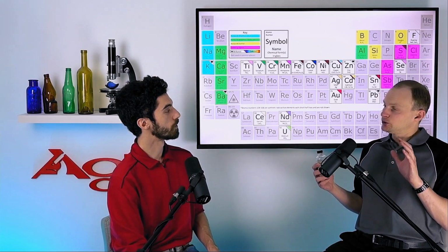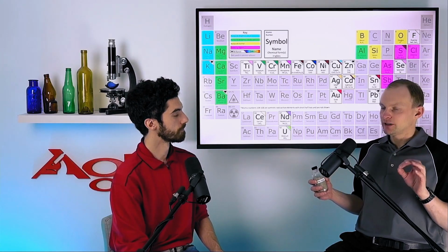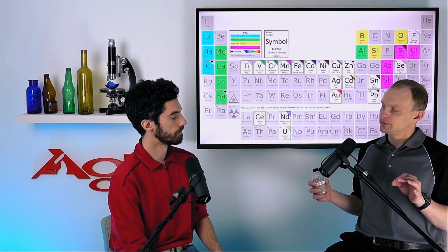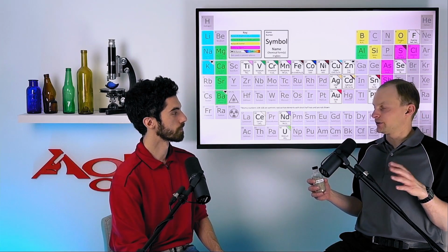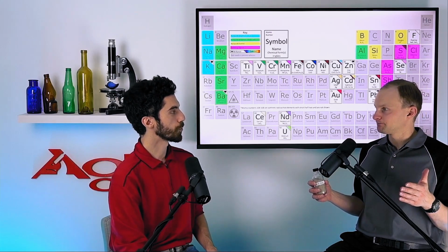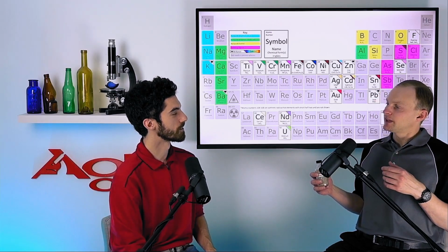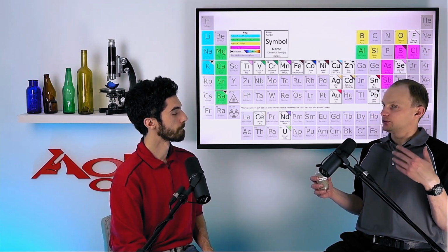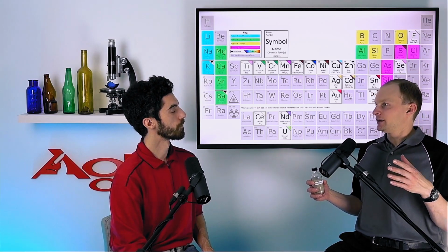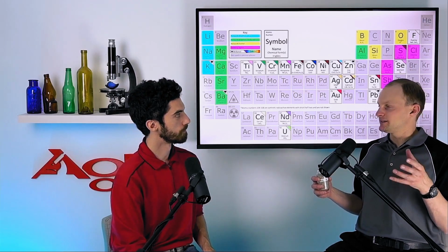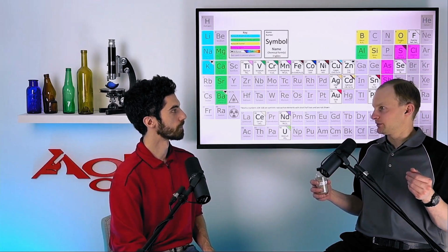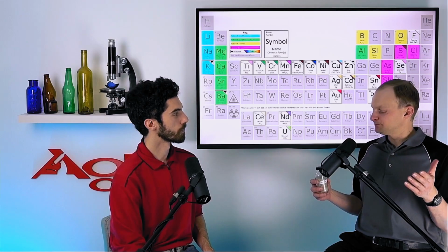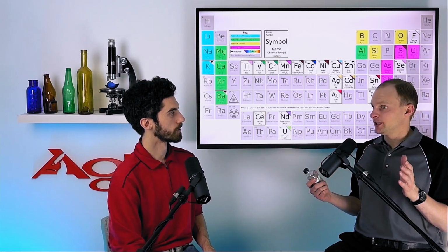Now, alumina is a very important minor component of glass, typically in the 1 to 3% range for a common soda lime silica glass. Still important, but nothing like sand. And it helps with the chemical durability. It helps it to resist attack by water and to maintain a nice appearance. It doesn't get fogged up over time with that addition of alumina. Sure. So we need to have that alumina in there.